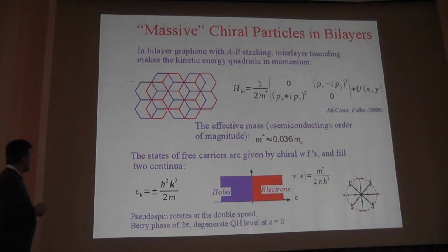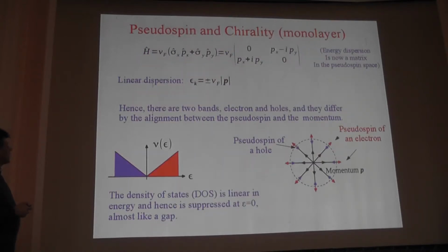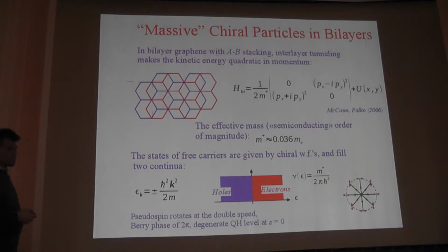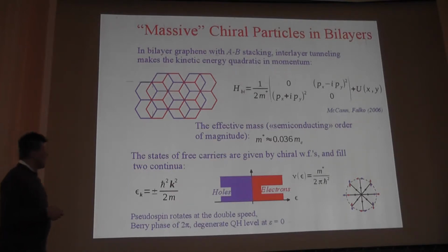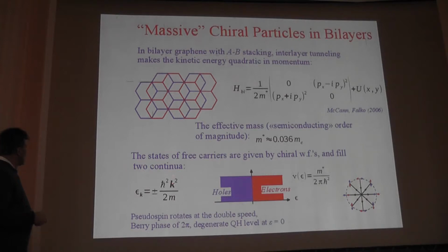What happens is that the electron state here on the red side couples to the one on the blue side. They acquire large energy and go out of the game. So what remains in the game is the electron states on the sides, and the resulting band structure has this form. You can notice that what has changed is that px minus i py is now squared. Again, you have some alignment between the direction of the pseudospin, which basically means top layer or bottom layer, and the momentum. A similar diagram has this form: the pseudospin rotates twice as fast as the momentum. Since the energy is proportional to p squared, this portion is unsurprisingly momentum squared.